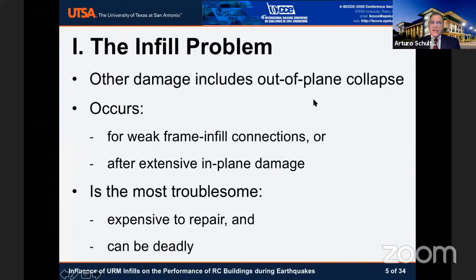We can also have out-of-plane damage, and that's probably the worst. And this will occur because the connections between the frame and the infill are weak, or they're separated if there's a gap, or if there's damage to the infill due to in-plane loading that produces the diagonal cracks that we saw earlier, and then under out-of-plane loading, there's nothing to resist it in the panel, and so it simply collapses out of plane. This tends to be some of the more troublesome damage in infill panels. It's expensive to repair, and as I mentioned earlier, it can be deadly.